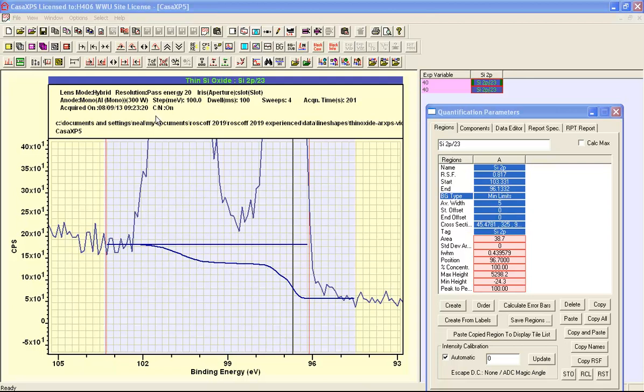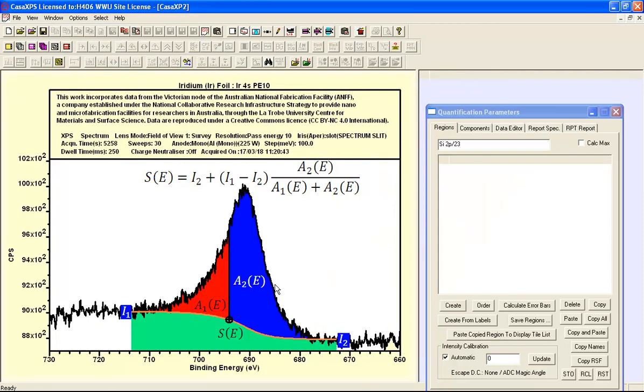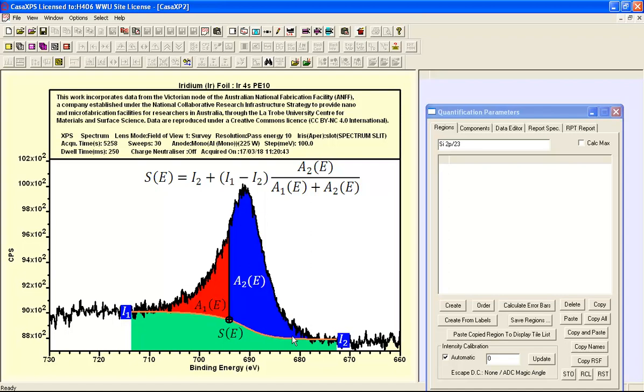We can see this if we look at the calculation for Shirley. This is the basis for a calculation. It's the area, this A2 area, that is calculated and used to scale these intensities I1 and I2 as you go across an interval. So all of these data, and in our case we had silicon, both oxide and elemental, all would be included in this Shirley calculation.